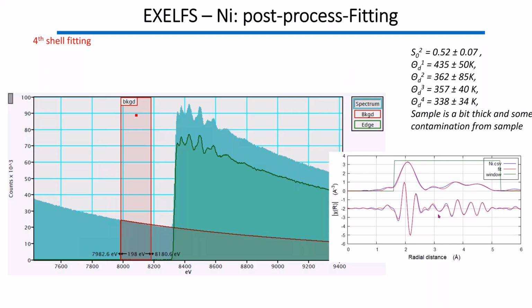But this is a good point, because recently we've been using even faster scanning, since the direct electron detector has a very high detection efficiency. We can use faster scanning and longer time, keeping roughly a similar total dose, but improve the data quality and reduce the damage. Yes, if you do fast scanning, the beam damage can be reduced a bit. We haven't quantified how much, but we can see a clear signal of mitigation of the beam damage. But still, for oxides or similar materials, one has to be very careful doing that.